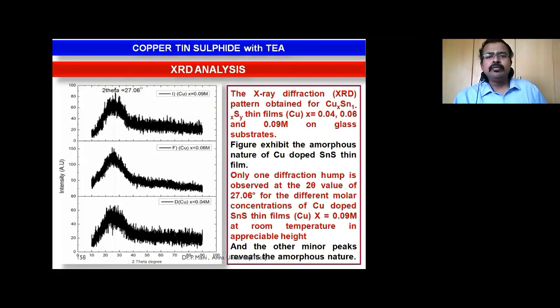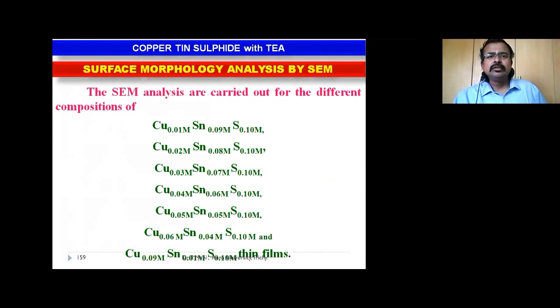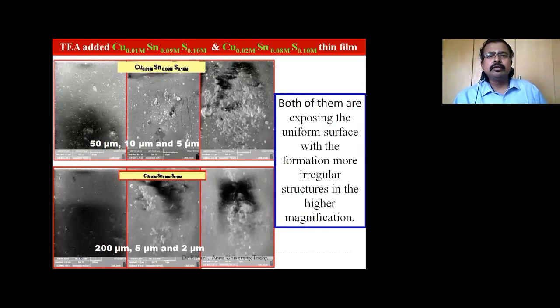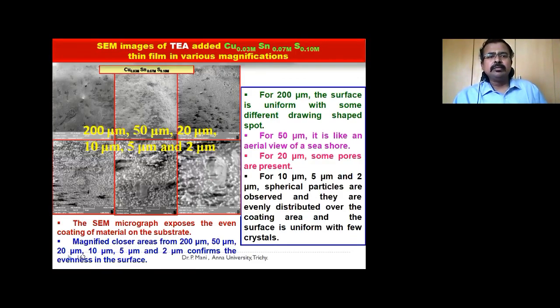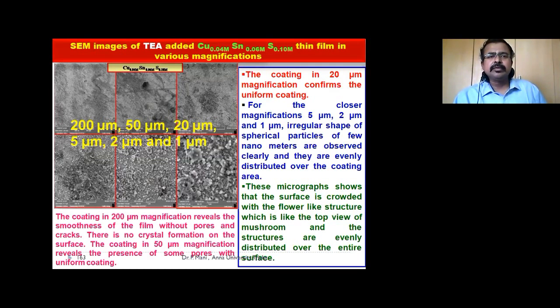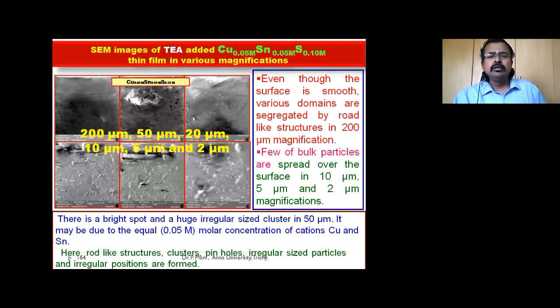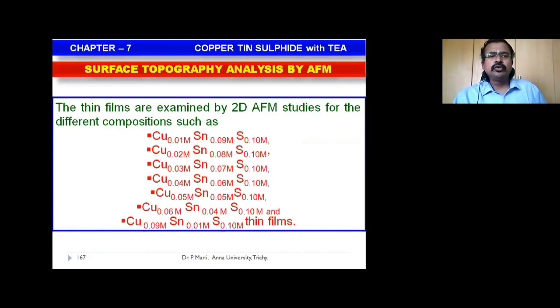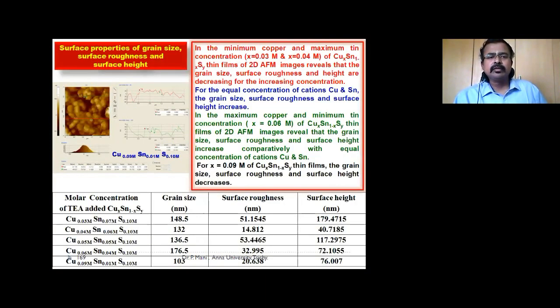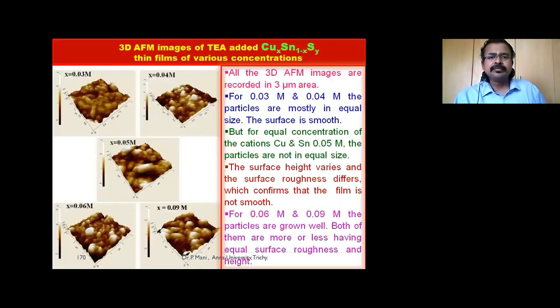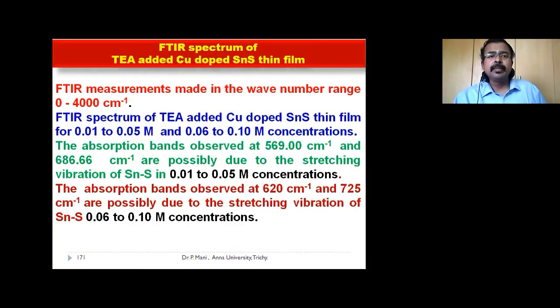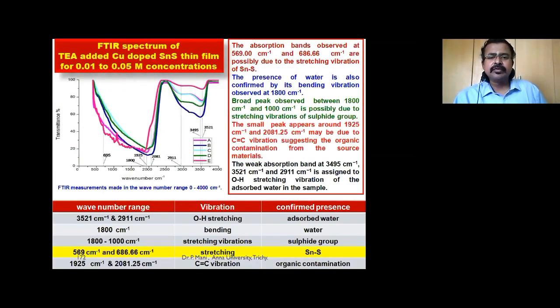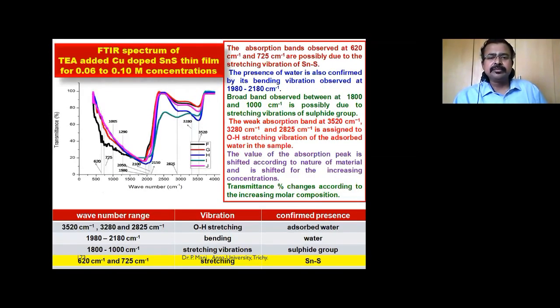Material preparation we know, and we are getting amorphous. Surface morphology is good for this. We are seeing SEM images in various sizes for copper tin sulfide in various molar concentrations. Surface topography by AFM: we are seeing different grain sizes, surface roughness, surface height for different molar concentrations. We can see uniform coating. Then the FTIR spectrum for this CTS added with TEA, we can confirm tin sulfide, presence of water and contamination, everything.